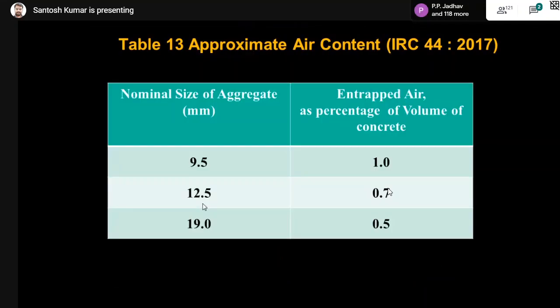Now, air content is available. It is in the concrete. You cannot escape it, as discussed. But one thing you have to note is, air content is designed for different grades of concrete in a different dosage. When you deal with a higher size of aggregate, that means the nominal size of aggregate is 9.5, 12 or 19, the entrapped air percentage is also less. That you have to make it clear.